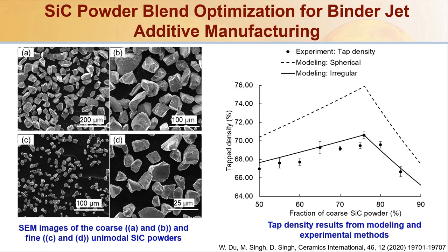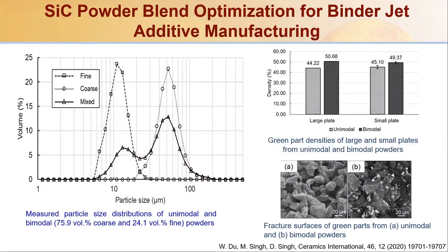What we then did was try to use the same fraction of coarse and fine powders and make some materials, roughly around 75-25% powders. One critical point I would like to make here is that silicon carbide powder blend optimization is very critical in getting initial high density of binder jetted parts.